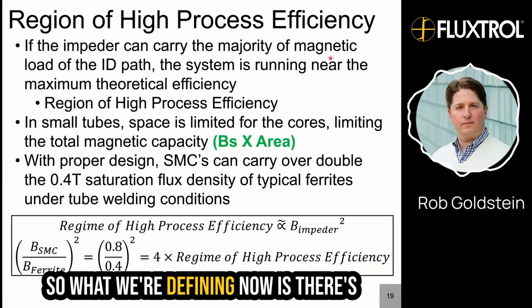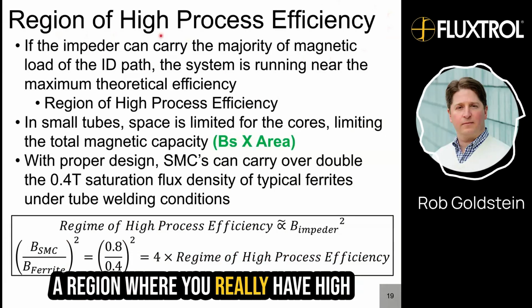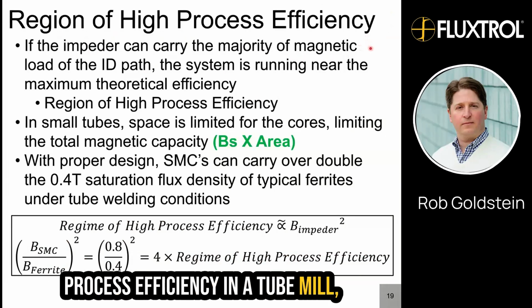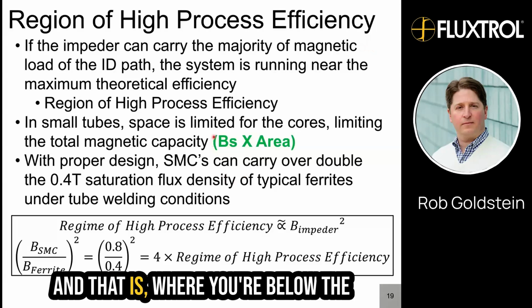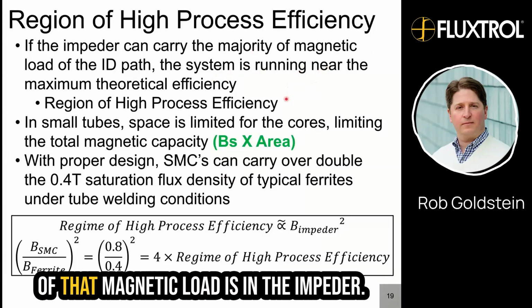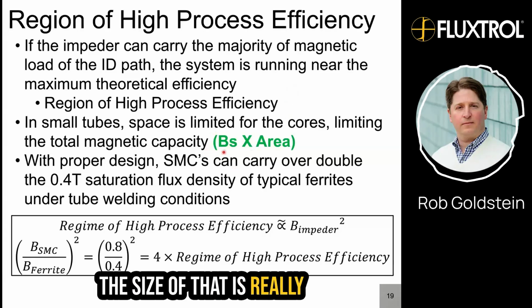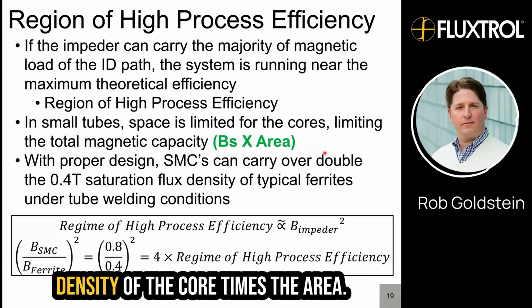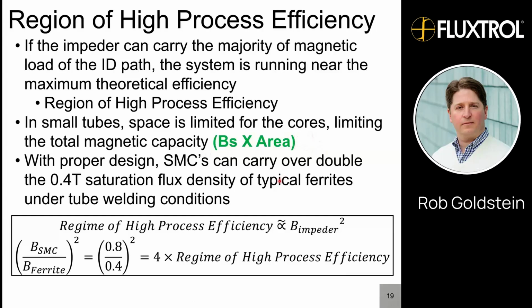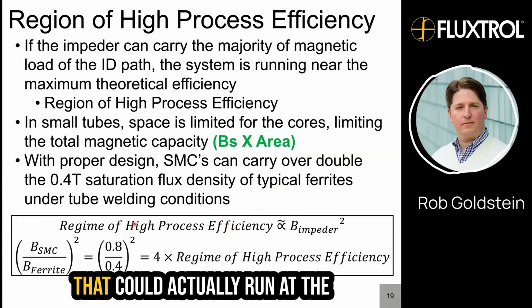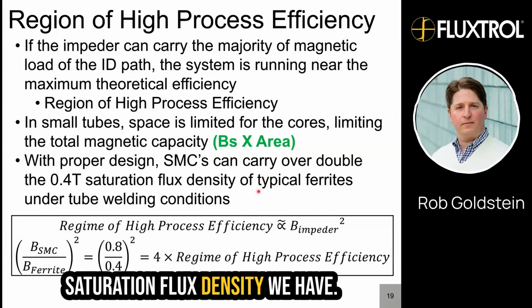So what we're defining now is there's a region where you really have high process efficiency in a tube mill. And that is where you're below the magnetic permeability limit, and the majority of that magnetic load is in the impeder. The size of that is really potentially the saturation flux density of the core times the area. So we still haven't found a line that could actually run at the saturation flux densities we have.